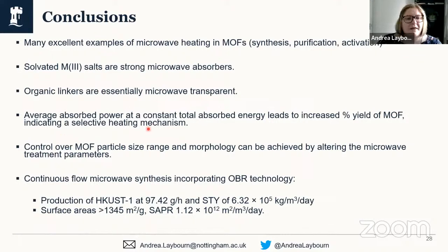I've then shown you that, using a bespoke purpose-built reactor where we delivered a constant energy, but delivered that at a low power for a long period of time or a very high power for a short period of time, we can see that the amount of absorbed power increases the percentage yield of the MOF that we are producing. And this indicates a selective heating mechanism where the metal ions in solution heat before the heat is then transferred to the linkers during the synthesis. And this is in keeping with the dielectric properties measurements.